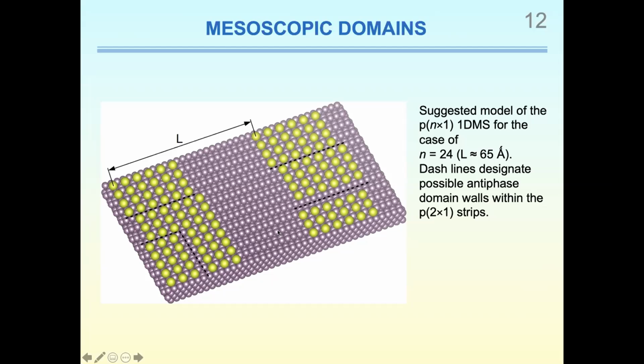As was already pointed out above, the half-integer order spots are rather broad along the 1,1-1 direction, indicating the presence of disorder. It's a natural consequence of a translational degeneracy of the primitive 2x1 lattice along this direction, namely two equivalent positions of the unit cell of this superstructure can exist, and both are present within the stripes here. Consequently, that layer consists of two equivalent domain types separated by domain walls, dashed lines.